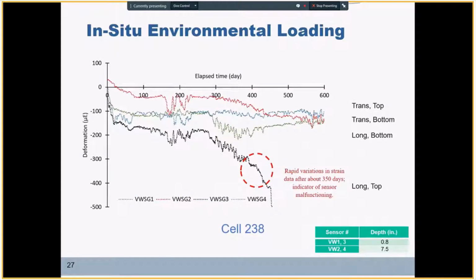The same type of data for cell 238. Unfortunately it seems we're losing one of the sensors - the one at the top - with a rapid increase in strain numbers, meaning we're most likely losing that sensor. But overall, comparable performance and magnitude of numbers for the two pavements, so no significant observation or abnormalities that could be traced back to the binder content. Everything normal here.